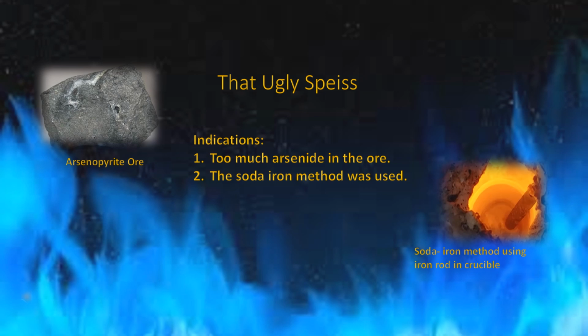Once the slag is cooled and the button removed, and during examination you noticed a hard tin white bead stuck to the lead button, no problem, just cupel it. On the other hand, if it was coated, then the button would have to be redone in a crucible or scorifier. This ugly coating is a good indication that the ore had a high concentration of either antimonides or arsenides, most likely arsenides or arsenic. In this case, a smaller sample size would be in order.